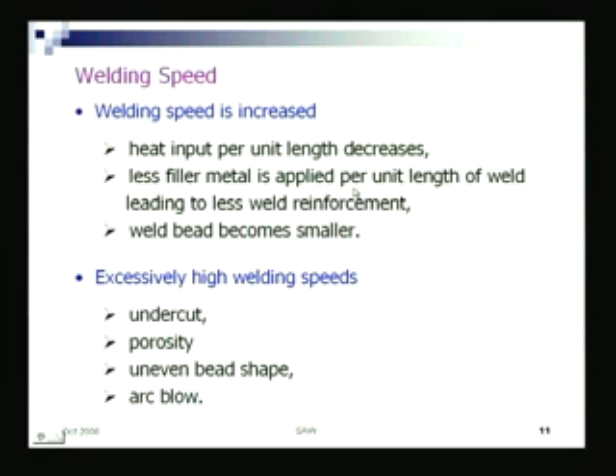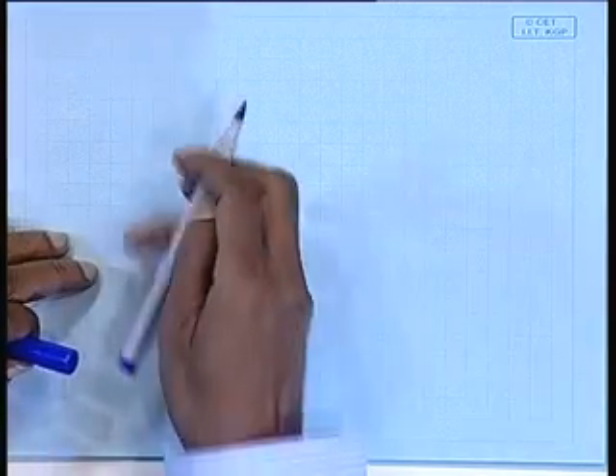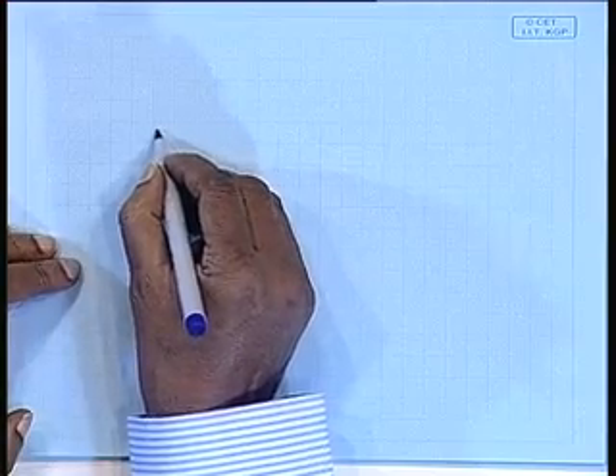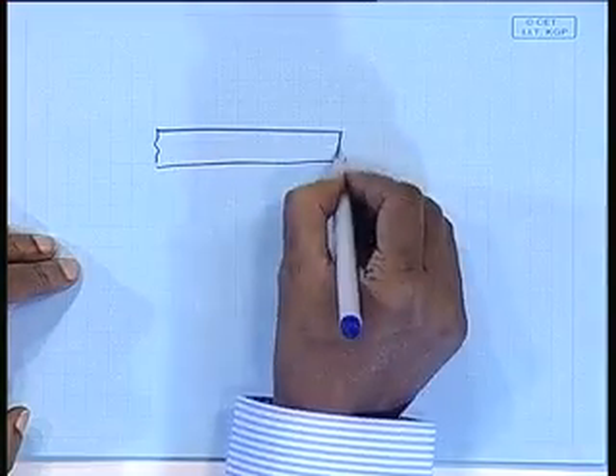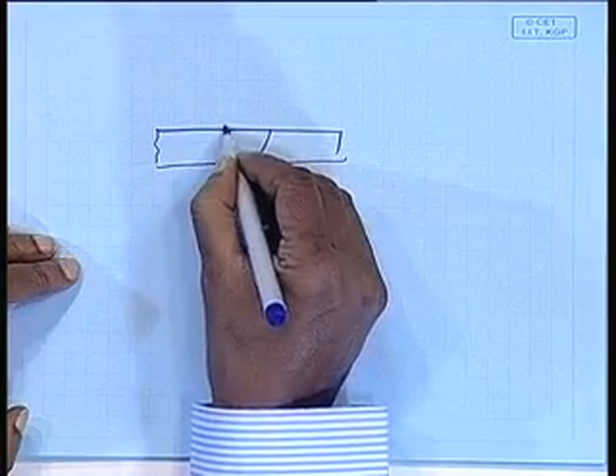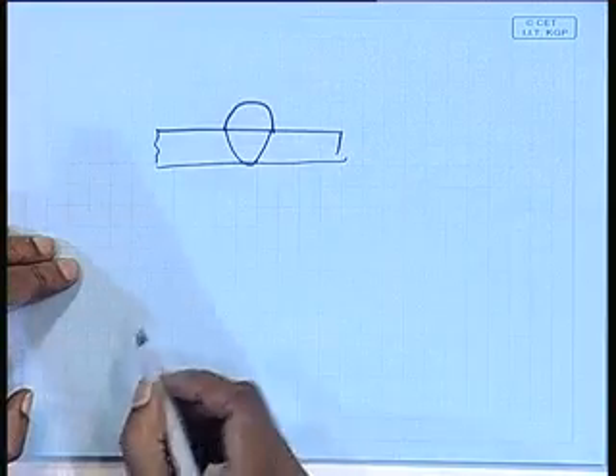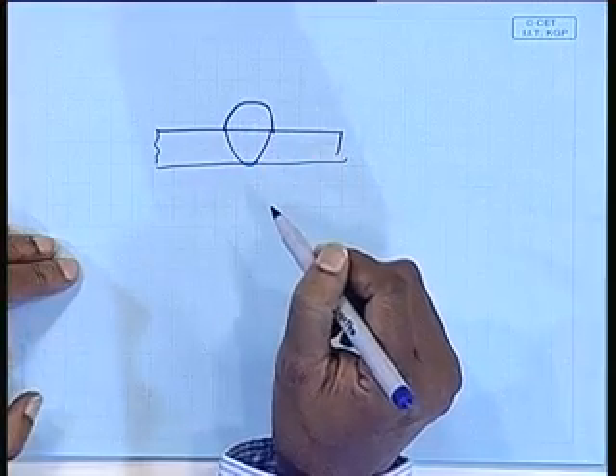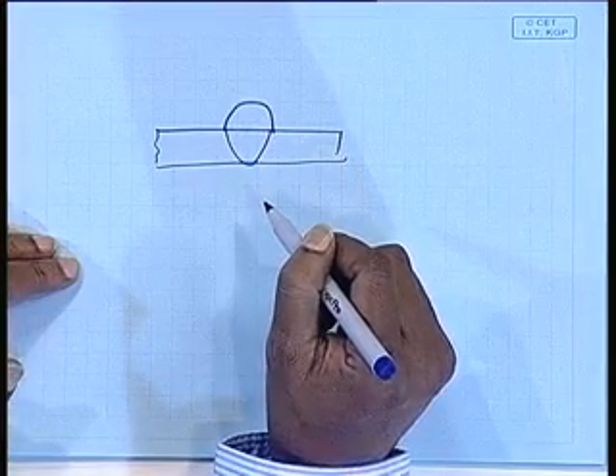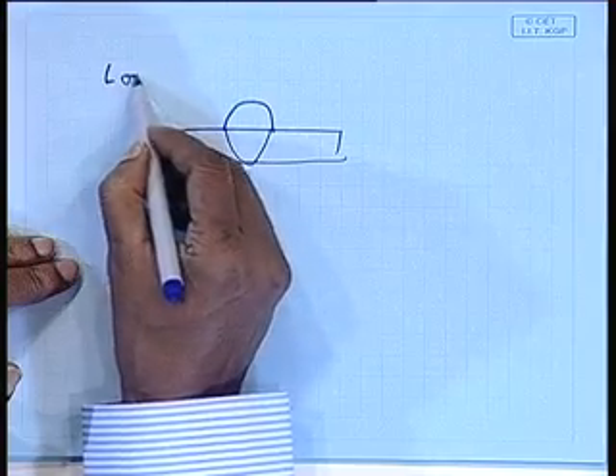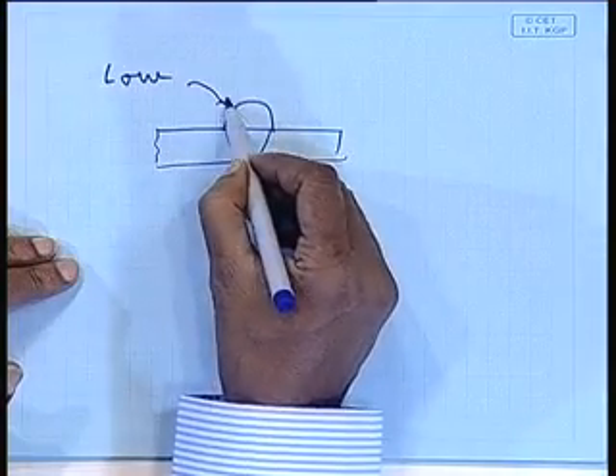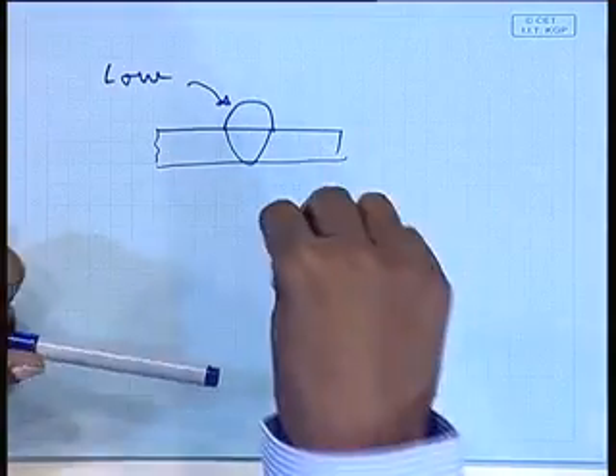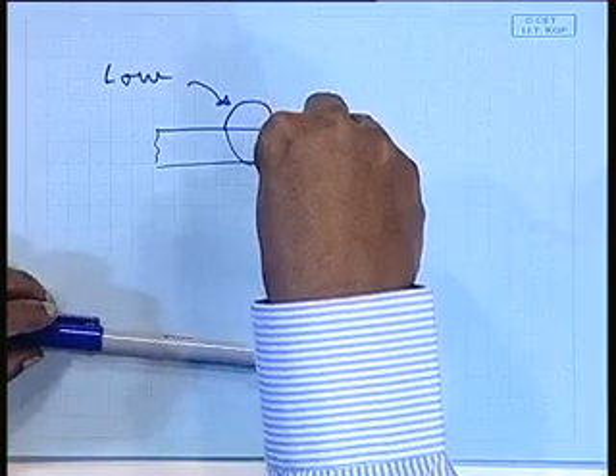Less filler metal is applied per unit length of weld, leading to less weld reinforcement. If the welding speed is low, then it may lead to over deposition. This is what over deposition is, if the welding speed is low. If the speed is low, then obviously more metal is getting melted and getting deposited at a place.